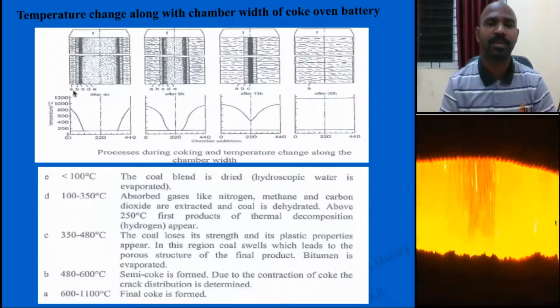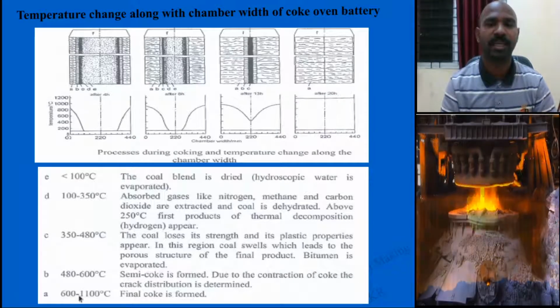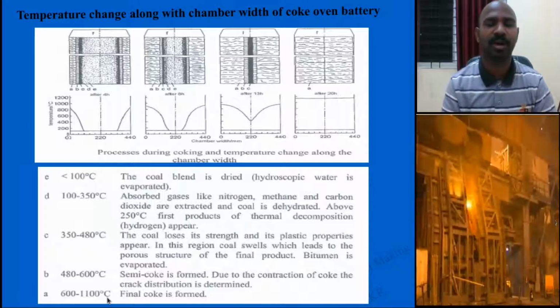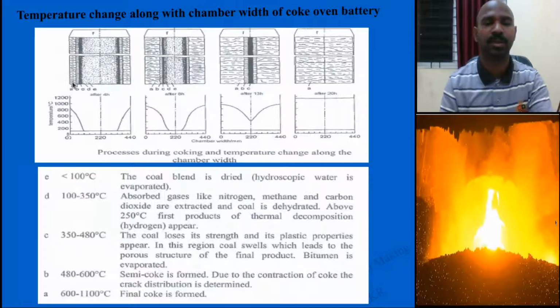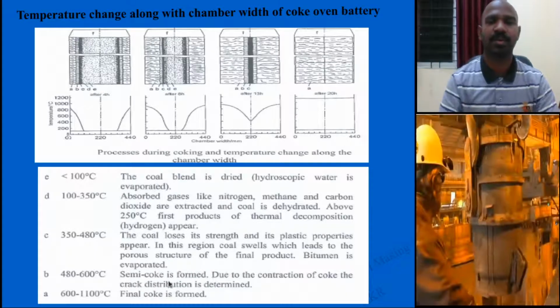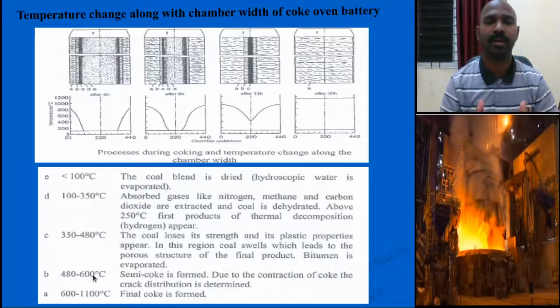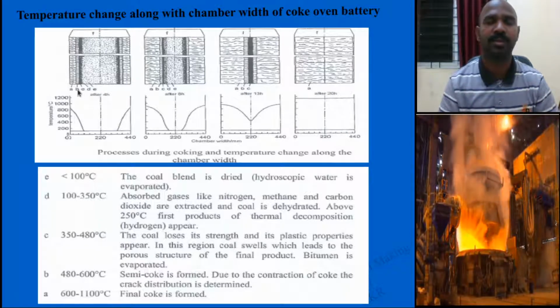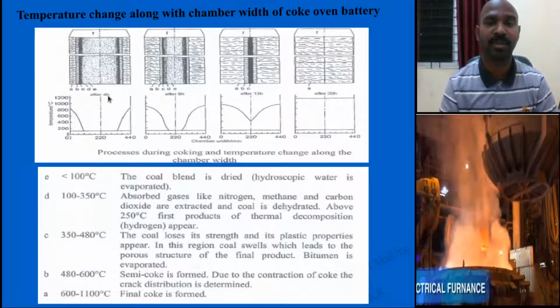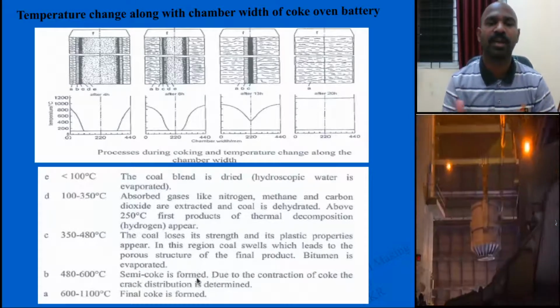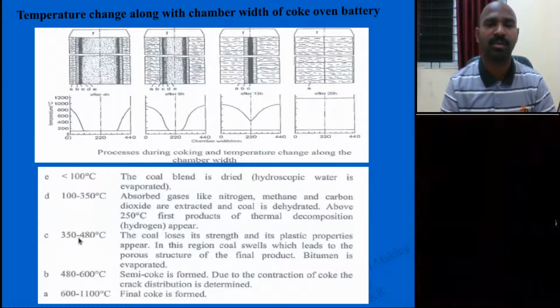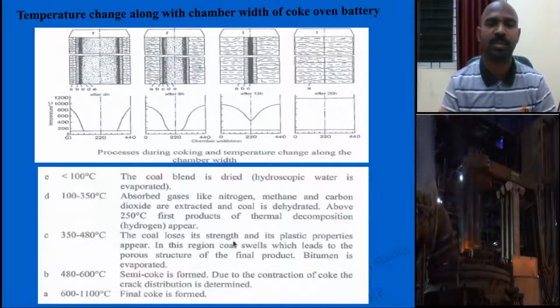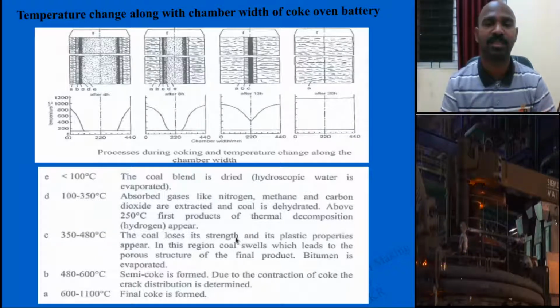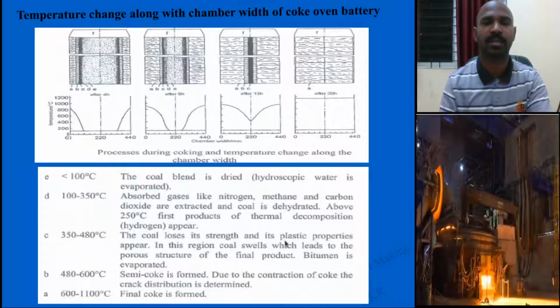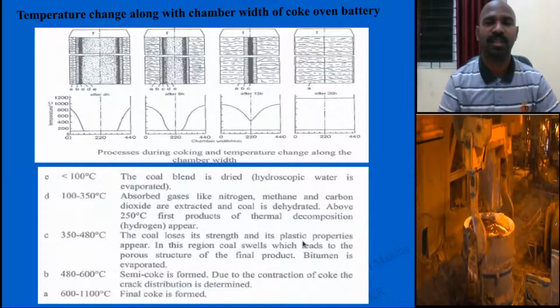For example, if you see A, this A corresponds to the temperature of 600 to 1100 degrees Celsius, which is final coke. Only this much width in the entire chamber, this much coke is formed. And coming to the semi coke, 480 to 600 degrees Celsius, that is B. In the case of after 4 hours, which is semi coke, not completely coke is formed. And C is 350 to 480 C, where the coal strength is going out and converted into coke strength. Semi-plastic to plastic changes will occur.